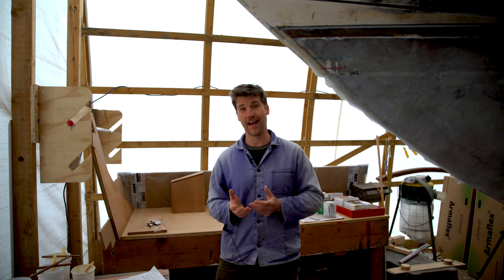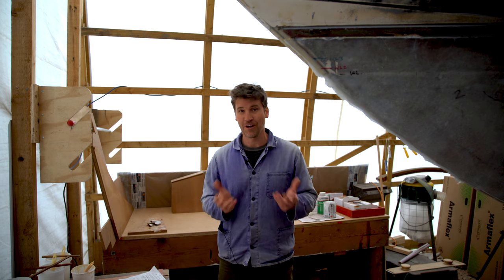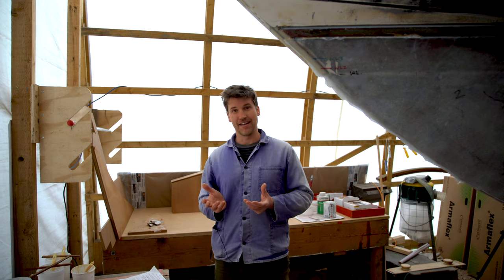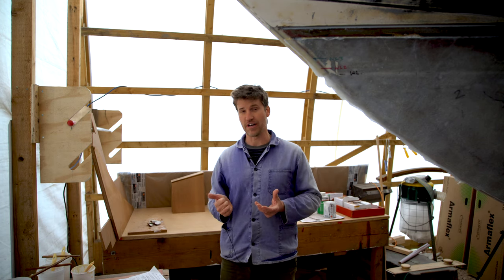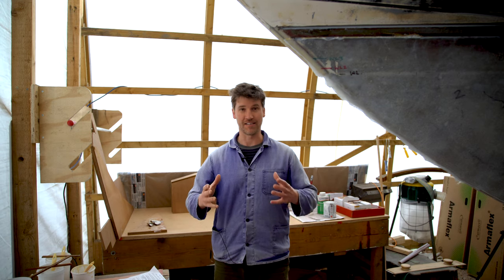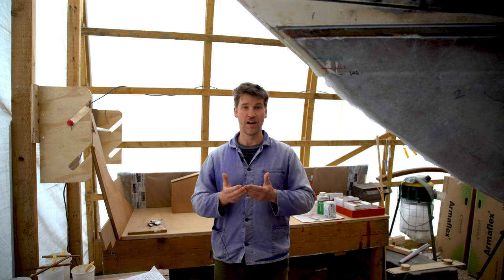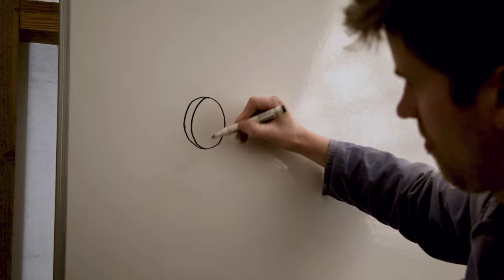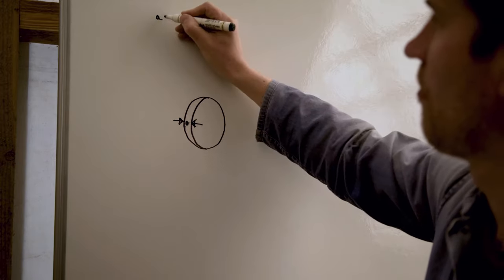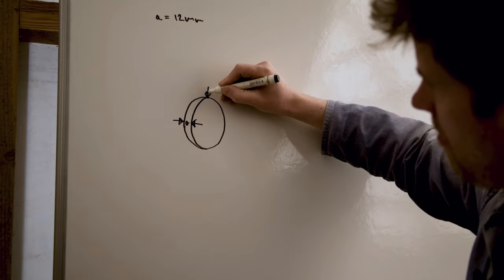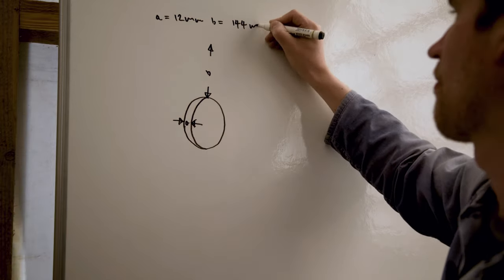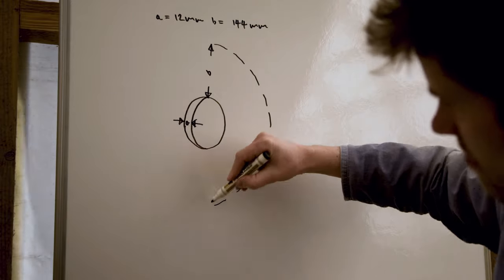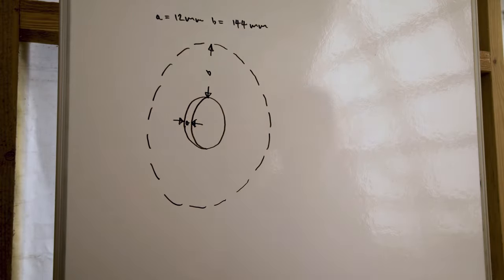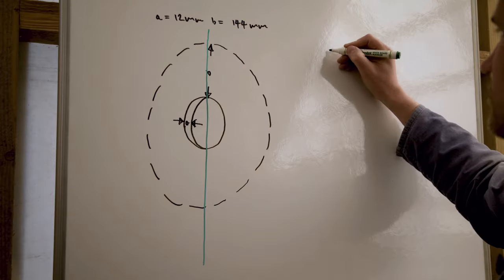So when is the expense of epoxy actually justified? Well, quite often it simply isn't. And the only times I'll consider using it are very specific. Usually when the repair area is somehow constricted, so I can't get a good bonding area. The area of any repair is determined by the thickness of the laminate. With this hole, it's 12 millimeters. The optimum scarf angle for this is 12 times the thickness of laminate, which in this case is 144 millimeters.